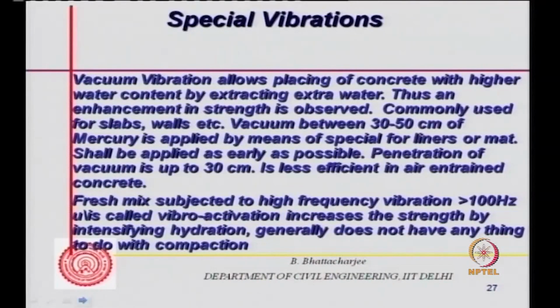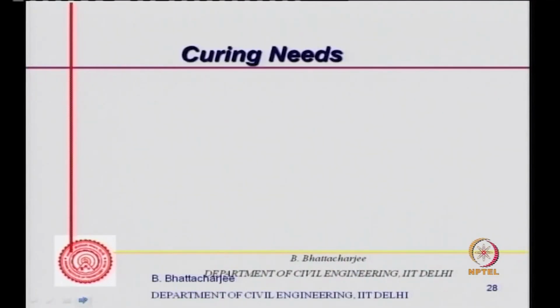Fresh mix subjected to high frequency vibration, over 100 Hz, is called vibro activation. It increases the strength by intensifying hydration, and generally does not have anything to do with compaction. So if you have used high frequency vibration, then the hydration process increases, nothing to do with compaction. Right, so these are special cases.